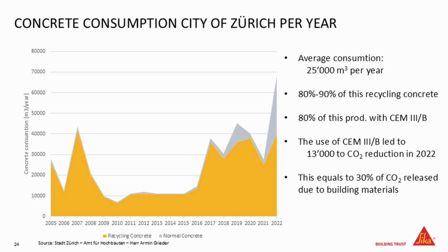There are some limitations for some applications. That's why we still have some normal concrete there, because you cannot use the recycling concrete for everything. But 80 to 90% is used, and 80% of this is used with CEM 3B. So that has a big impact. It's not just a specification, and this is really done in Zurich. That resulted in 13,000 tons of CO2 reduction in 2022, and this equals 30% of the CO2 released due to building materials. So that has a certain impact.